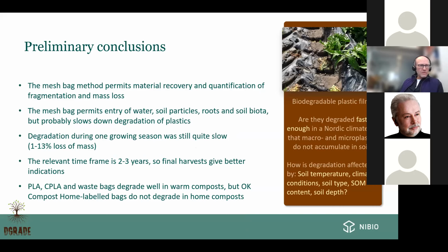So conclusions from this work is partially that this mesh bag method permits material recovery and quantification of fragmentation and mass loss for these films. It's a system which permits the entry of water, soil particles, roots or biota, etc., into the mesh bag, but it probably slows down the degradation rates compared to a single layer of plastic being incubated directly into soil. We are planning to try to compare these two degradation methods for shorter periods of time to see if we can find a sort of a transformation or a ratio between proper soil incubation and mesh bag incubation.